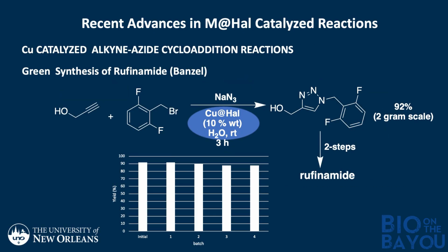Okay, we made a triazole that essentially is a precursor to rufinamide. This is an anticonvulsant being marketed as Banzel, but essentially, again, all in water. And again, we see the same level of recycling in terms of being able to use that catalyst again and again. Here, 4 times past the initial use without really any reduction in yield.